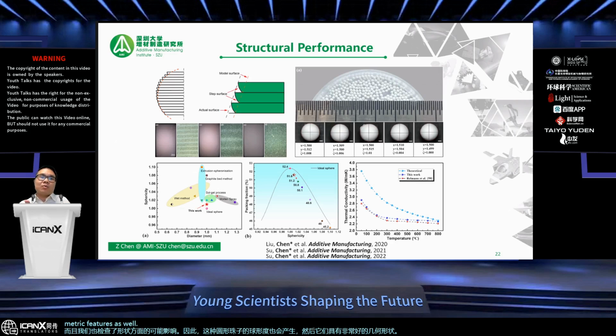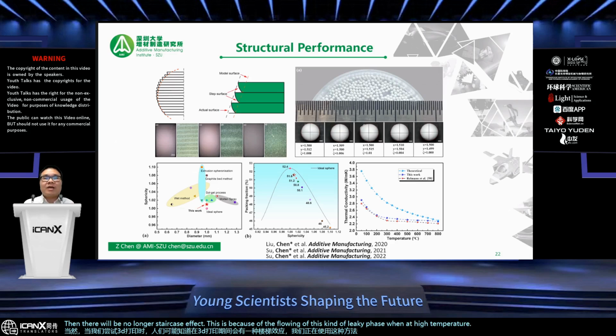And of course, when we try 3D printing, people may know that during 3D printing there will be a staircase effect. If we use this kind of method, then there will be no longer a staircase effect. This is because of the flowing of this kind of liquid phase at high temperature. So this will get rid of the staircase effect, get rid of the surface roughness, and there's no longer anisotropy in properties. There will be isotropic properties. So this strategy can be very efficient and useful for producing the breeding units.